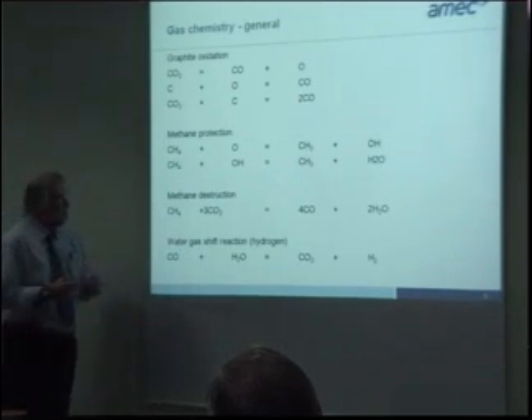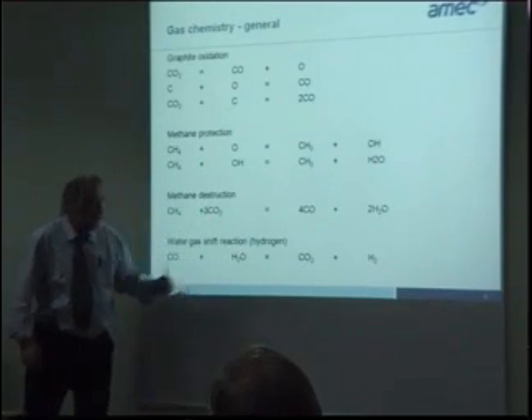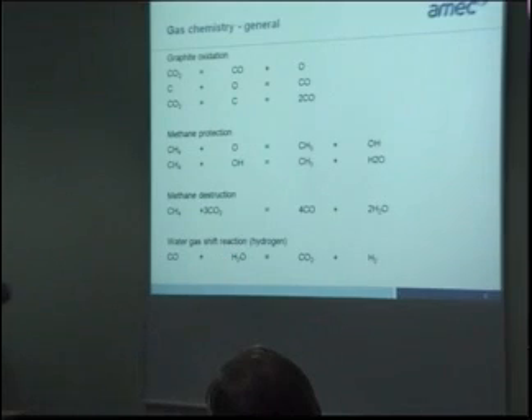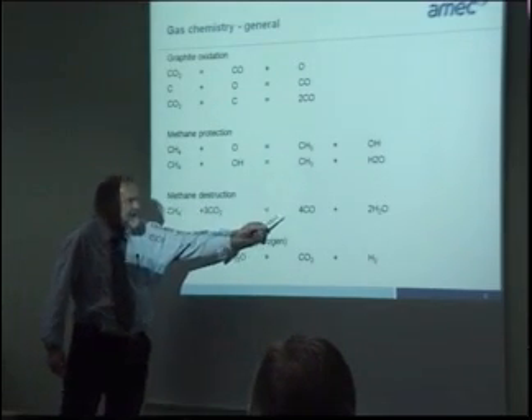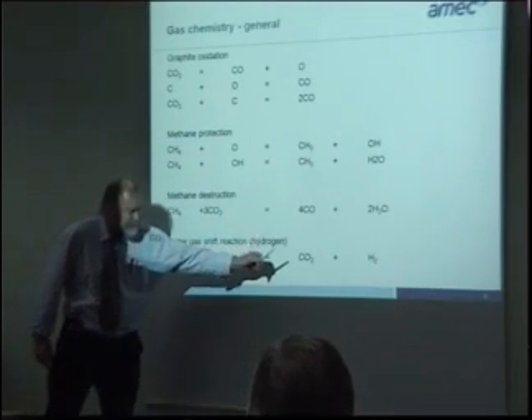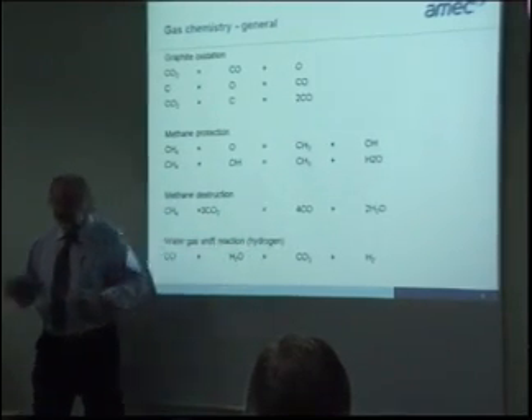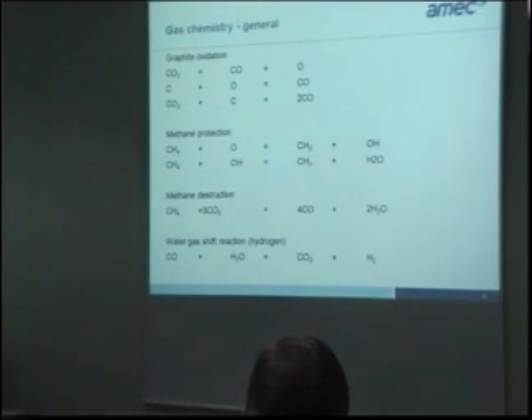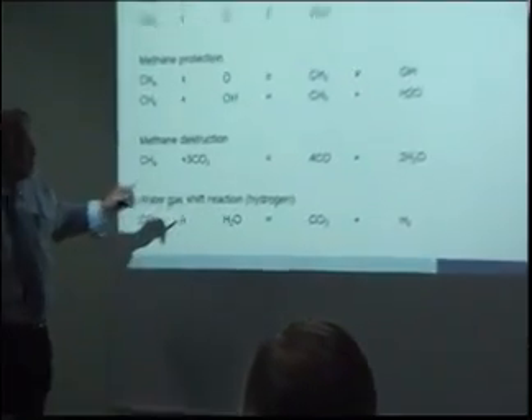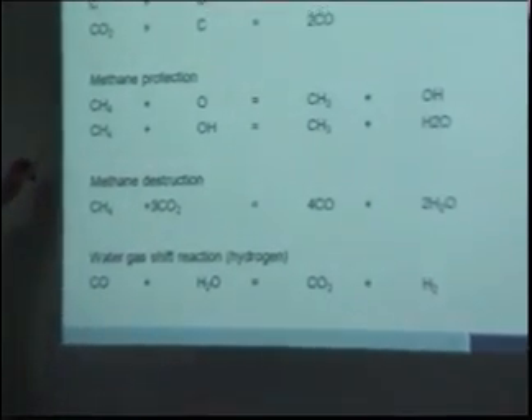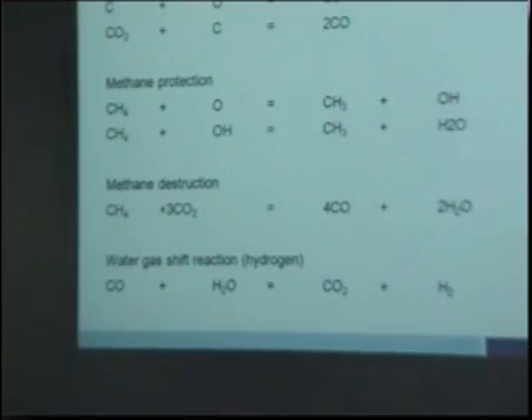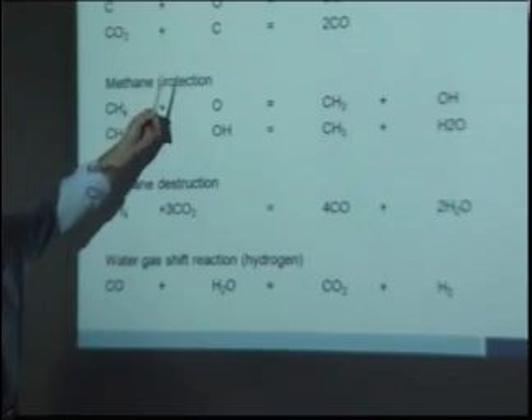Apart from the graphite mass loss, there's the steam production, which is not good at high temperature on steels. And there's carbon monoxide production and hydrogen production. Now, hydrogen isn't actually controlled in the reactor. You get what you get, but you do control the other species. We put about 240 parts per billion of methane in. Carbon monoxide is injected into the reactor at about 1%, and that's really to shift this reaction the other way, to slow down the oxidation of the graphite.